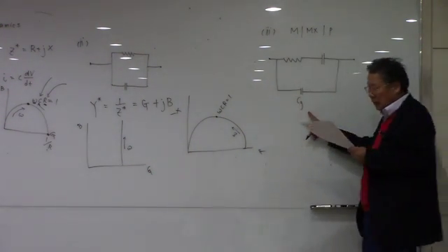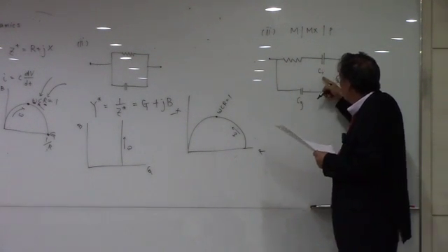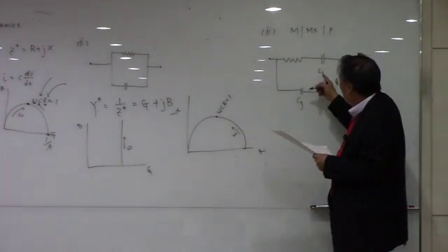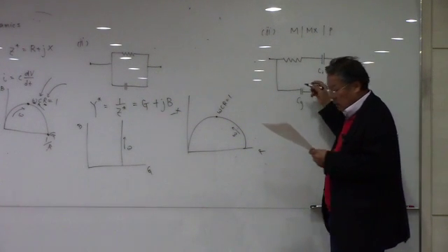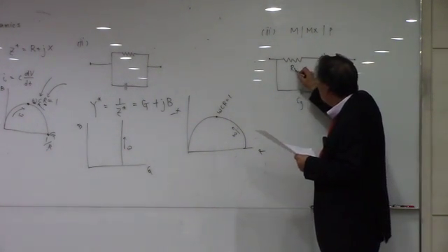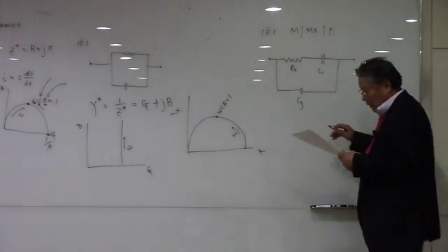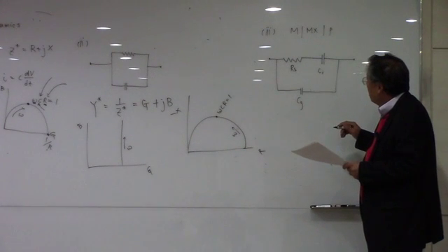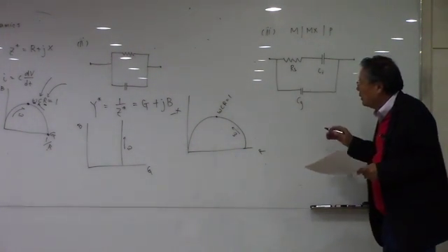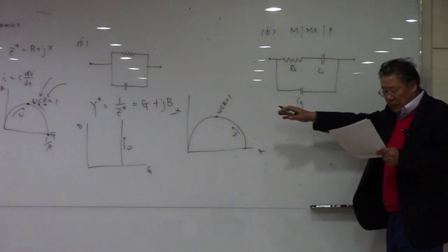This is a geometric capacitance, and this is a double layer capacitance due to the polarization, and this is a bulk resistance, including the internal resistance and everything, okay? We can approach this on the basis of this.